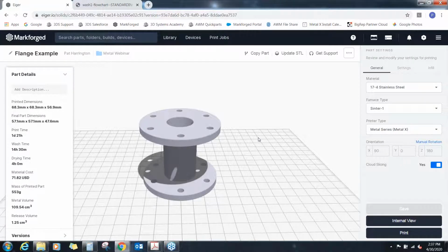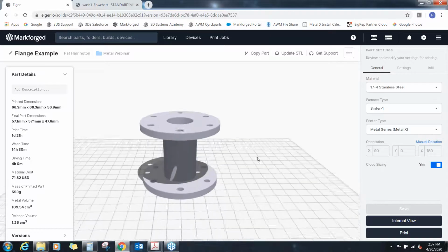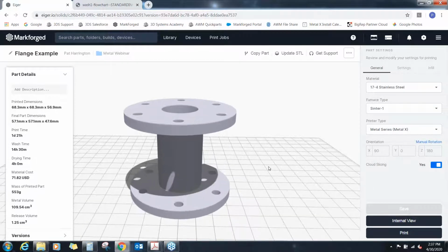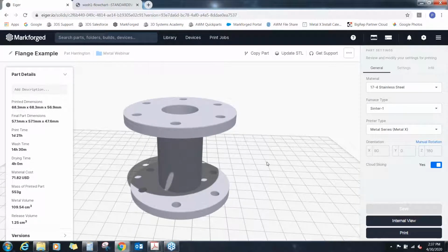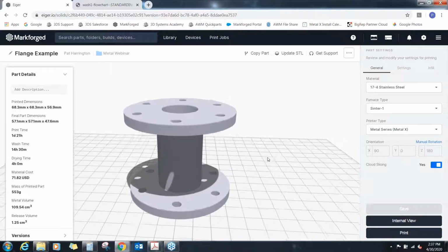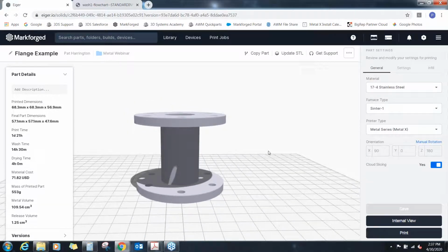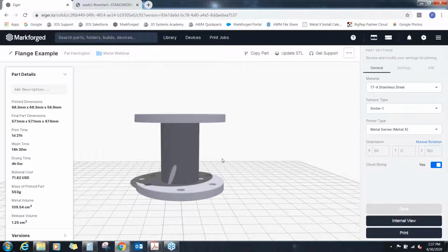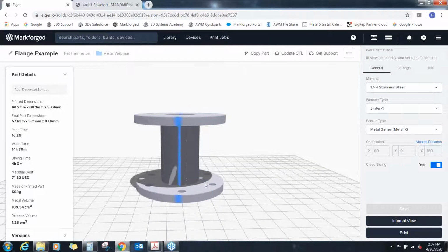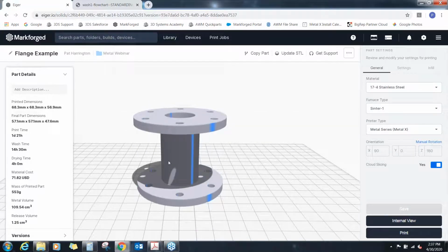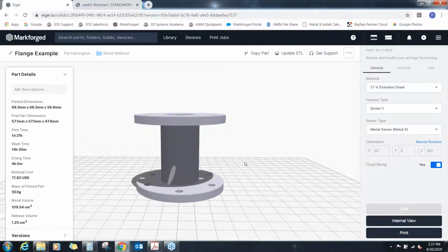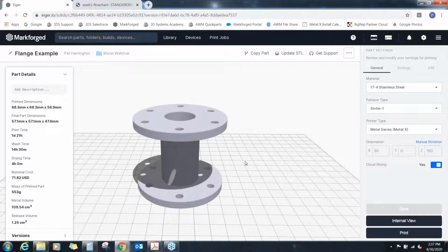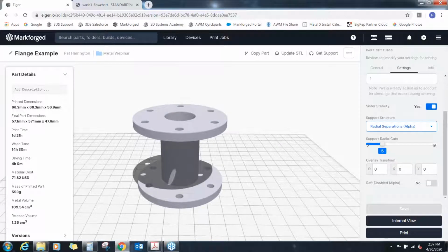So when we first got this machine, a geometry like this was very challenging, and basically we couldn't do it without getting creative with mechanically removing supports with maybe a Dremel or something. And the reason for that is the support material is going to be required underneath this upper flange, and it's going to connect the upper and lower flange. It's basically going to be a complete donut shape of supports around this inside neck, and there's no way to remove that donut shape. So that's why Markforged came up with an experimental print setting that we've had a lot of great success with in parts of similar geometry, which is Radial Separations.